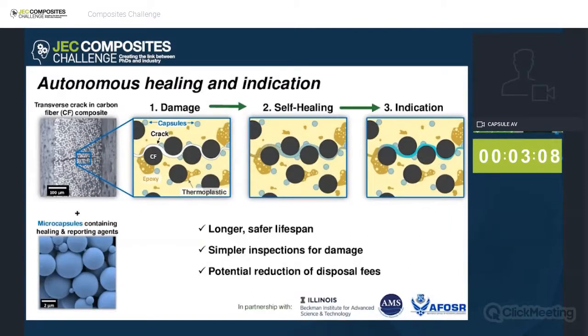This novel idea involves embedding tiny microcapsules containing both a healing agent and a special dye in our composites. To do this, we first mix a liquid solvent with a special dye that glows or fluoresces under UV light. And this dye is extra special in that suspending it in a solvent actually suppresses its ability to fluoresce or glow until that solvent is removed. We can then store this liquid mixture in tiny microcapsules, deposit the capsules on carbon fibers, and then embed these fibers in a thermoplastic toughened epoxy matrix.